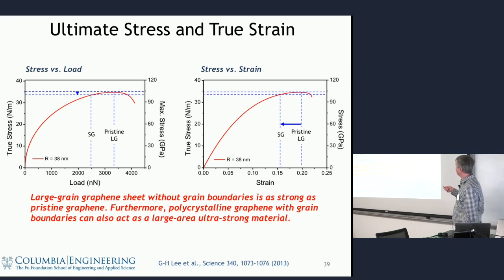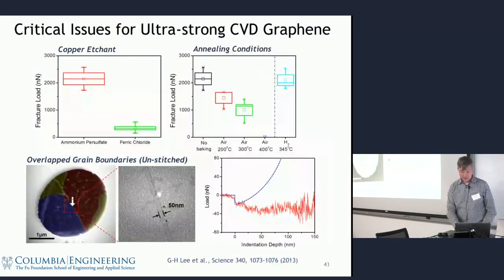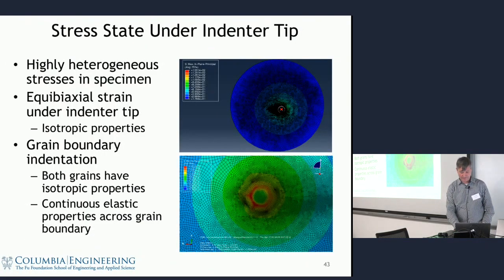The nice thing about the single grain boundary is that, we're using a different tip, but because you have the finite element modeling, you can eliminate all those effects and generate intrinsic properties. And what we saw was that right on the grain boundary, the strength was only about 10% less than the intrinsic material. All right, so we're running a little short on time.